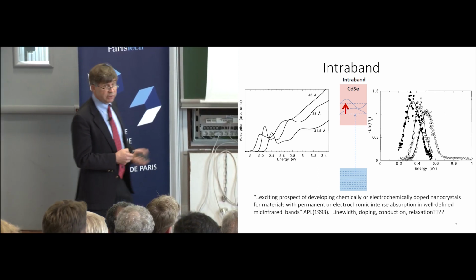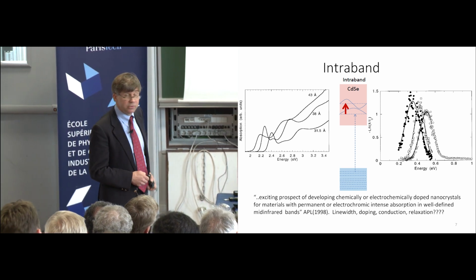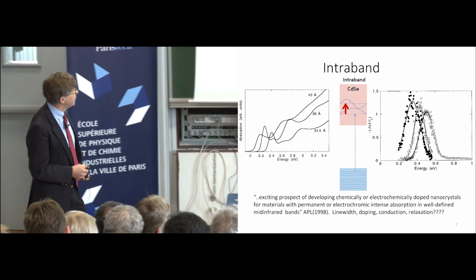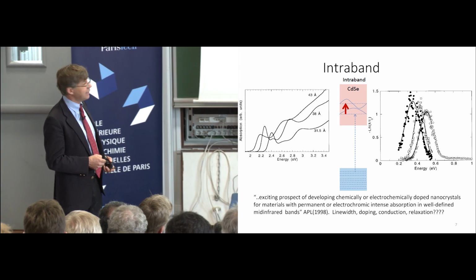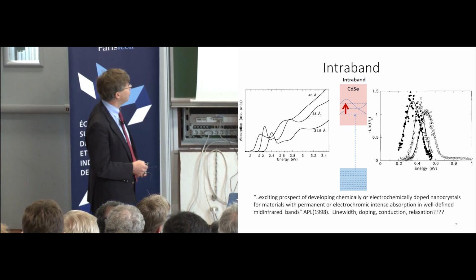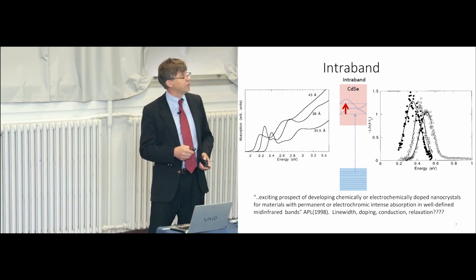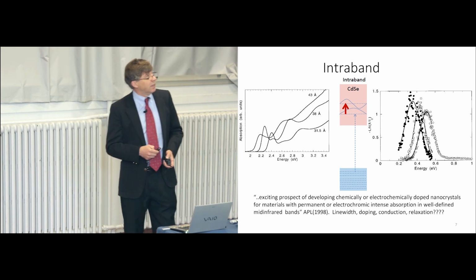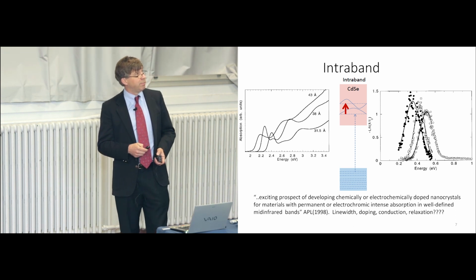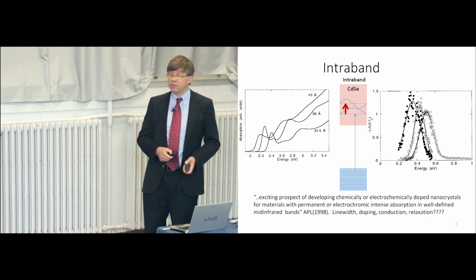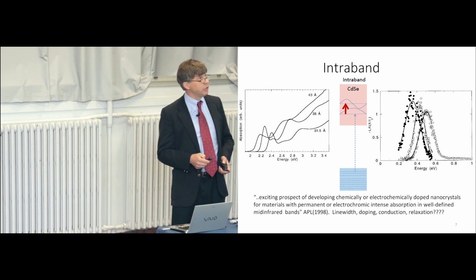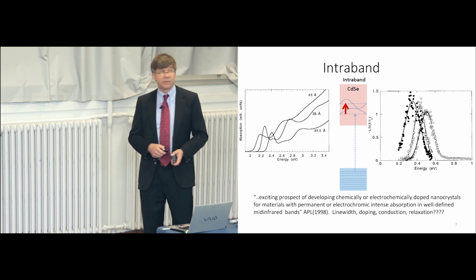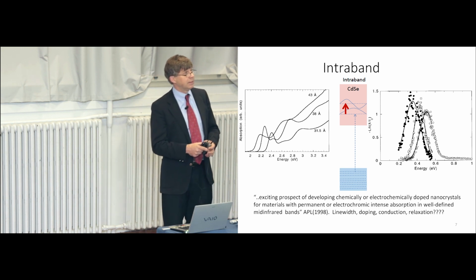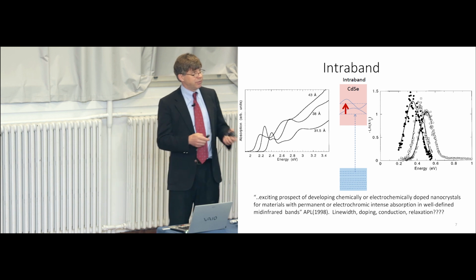And they would be perfectly tunable in the infrared, and my background was infrared spectroscopy. So it seemed very natural to try to detect those transitions, and they are called intraband transitions. And it worked beautifully. We had samples here of cadmium selenide, and when we did pump-probe spectroscopy, we saw those very intense infrared transient absorptions, which tuned with size, had about the right cross sections, and had the right tuning. And I got very excited by this.